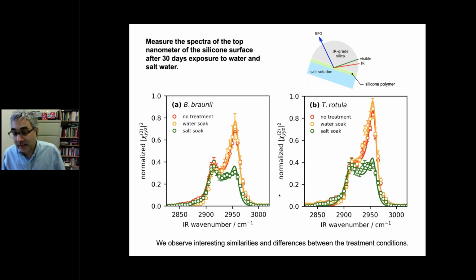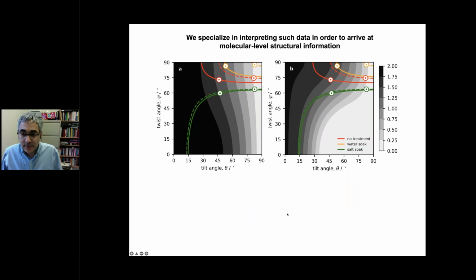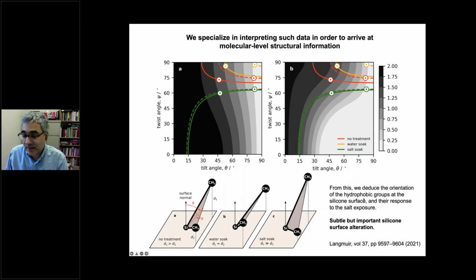So one of the main areas of interest in my lab is to take these spectra and to do some modeling to understand what does this mean in terms of the structure of the material. How can we understand this? And what we do now is we basically figure out how that molecule is oriented to give us this kind of picture. And basically what I'm showing you here is a silicon atom down below, and then we have one moiety, which is methyl, and another moiety, which is methyl, because every repeat unit in the silicone chain has these two methyl groups. And we can imagine a plane between these three moieties.